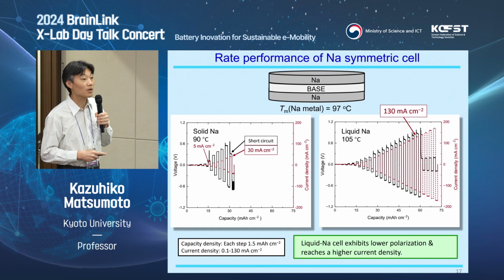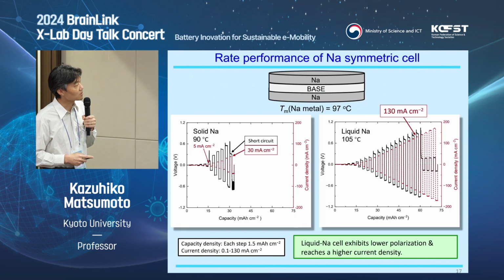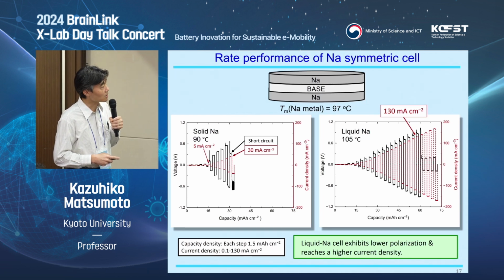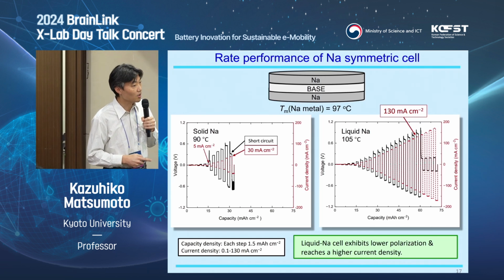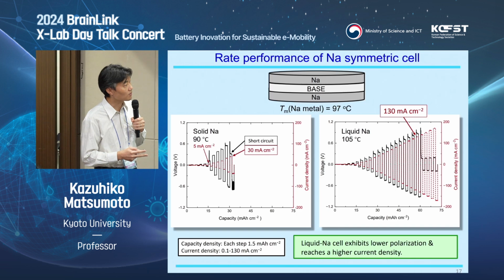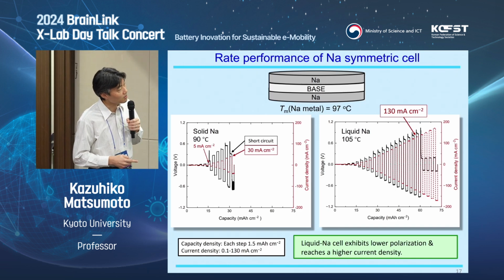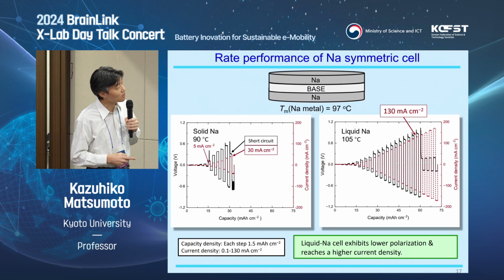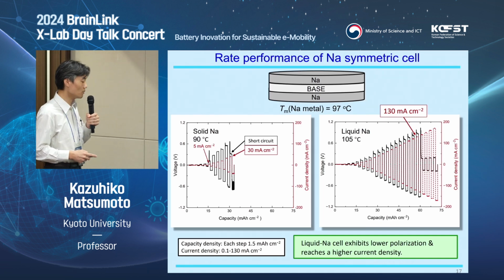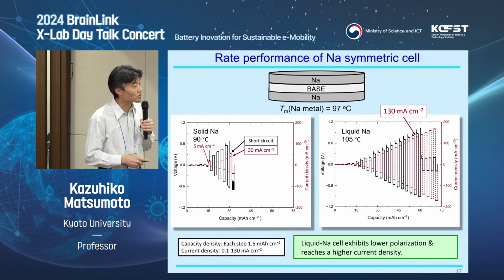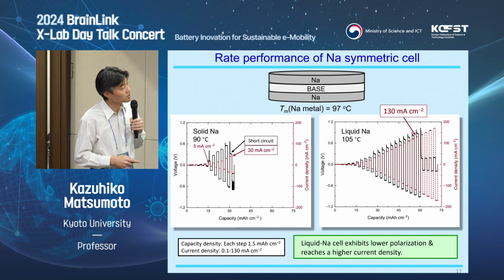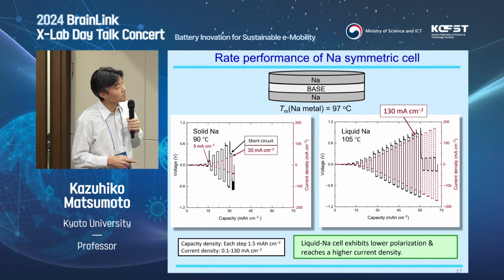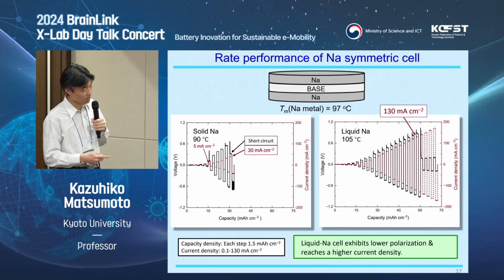So what we did was first we worked on sodium metal symmetric cells with solid sodium and liquid sodium. So both sides solid sodium and both sides liquid sodium in this case. And we see that the large polarization in the case of solid sodium metal compared to liquid sodium. Obviously from the bad contact between metal and beta alumina. And the big difference is the critical current density, where in the case of solid sodium metal, we see short circuit at 30 milliampere per square centimeter. But in the case of liquid sodium, it can go up to a very high current density of 130 milliampere per square centimeter.